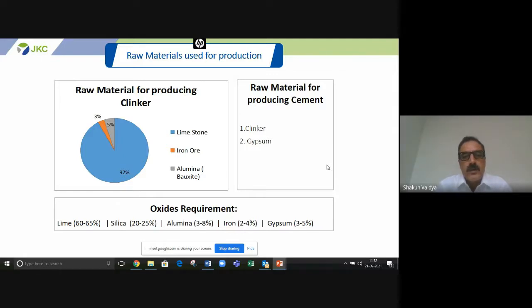And the typical oxide requirements are that lime should be around 60-65% in clinker, silica 20-25%, alumina 3 to 8, iron 2 to 4, and gypsum. Gypsum, as I told you, in the end we mix to retard the setting time. Unless this is mixed, cement may set instantaneously. So this is just to retard the setting time, which facilitates easy usage of cement.